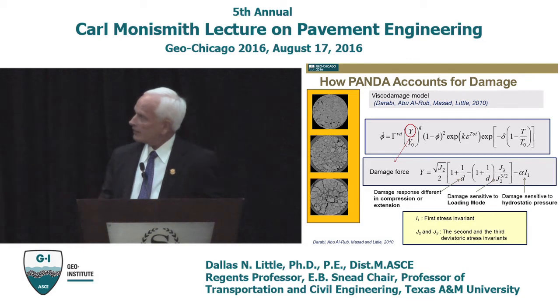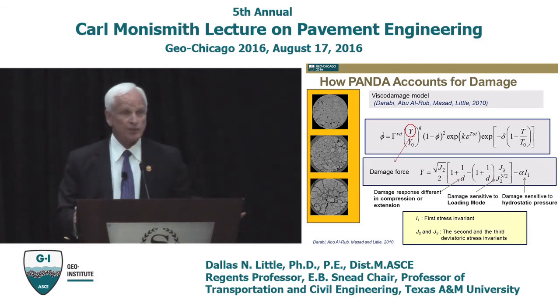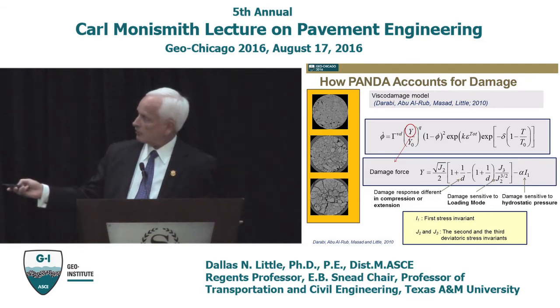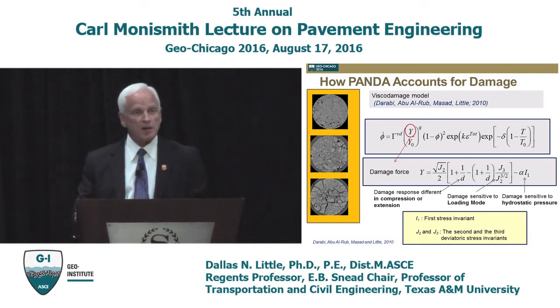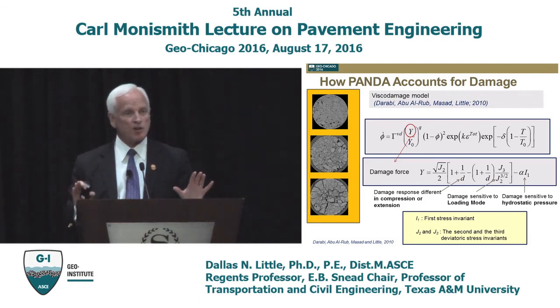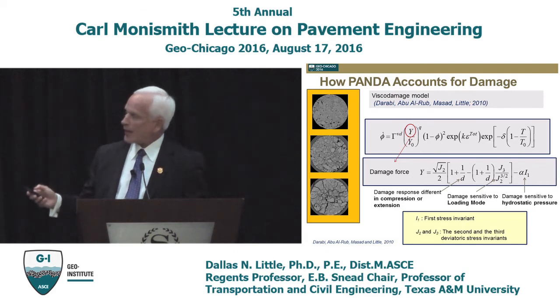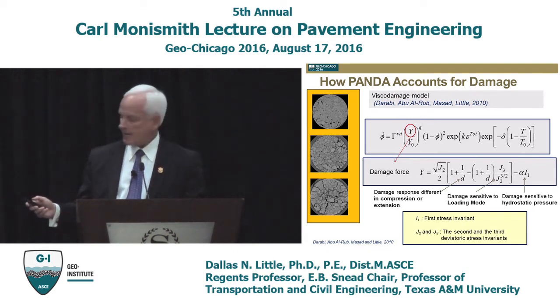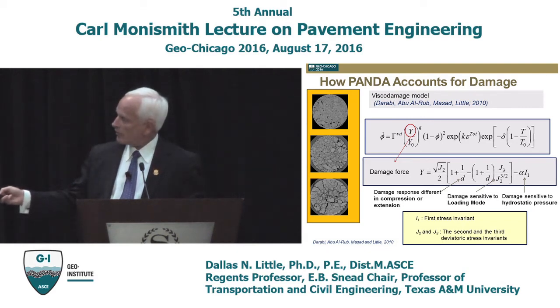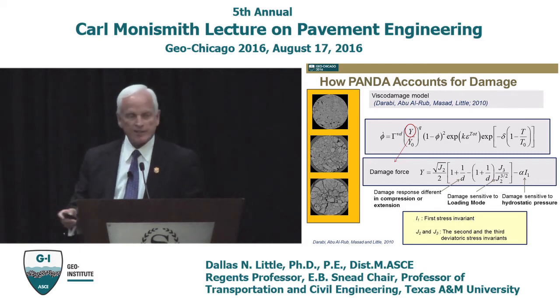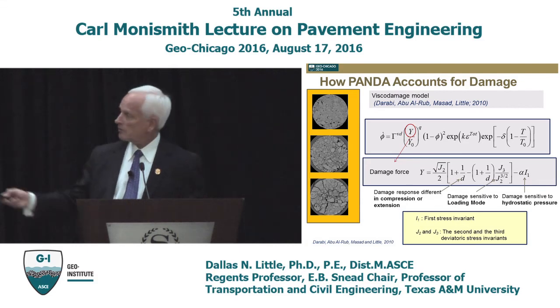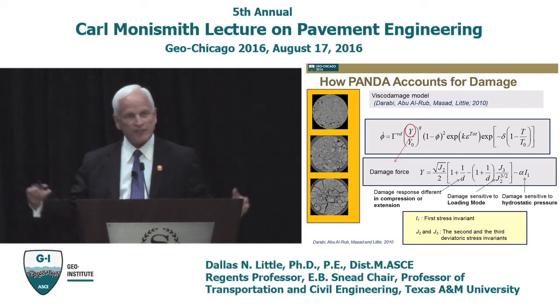Okay, so how does PANDA deal with damage? Well, just looking at the equation here, it's pretty complex, but we can simplify it down by talking through it. The driving force for damage is nothing more than this Y term, which is this Drucker-Prager type of a relationship between the shear stress that's developed minus the angle of internal friction times the confining pressure, I sub 1.